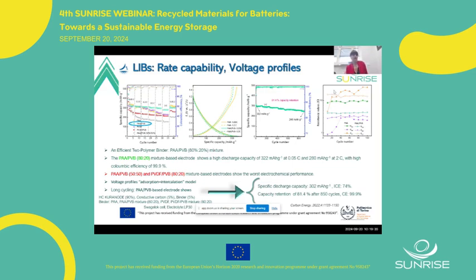So again, an efficient two-polymer binder system is PAA-PVB 80-20%. We also tried to evaluate the long cycling performance of this electrode, and as we show at 1C, the cell shows high specific capacity, very good initial Coulombic efficiency, and capacity retention of around 81% upon 900 cycles.